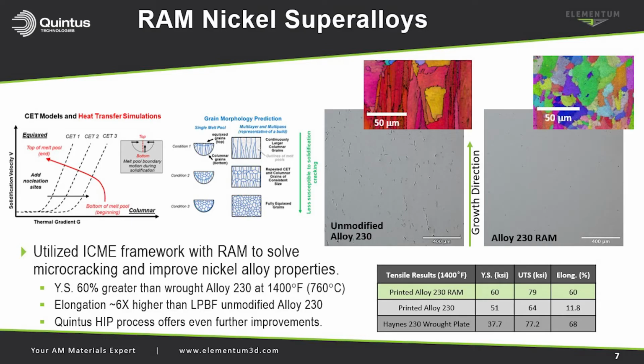With the gamma prime phase fraction alloys, we're also using the RAM process to improve the properties and performance of those alloys and eliminate the cracking there as well. So really leveraging some advanced technology and unique chemistry approaches to make these materials printable, improve their performance and reliability. You're also taking it a step further with the hot isostatic pressing approach, and that you're investigating the use of high pressure heat treatment in a modern Quintus HIP system, utilizing the uniform rapid cooling and even uniform rapid quenching to get the densification and steer the microstructure. Can you speak a little bit about high pressure heat treatment and what opportunity that creates?